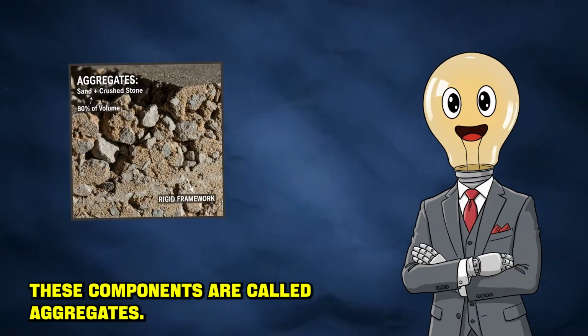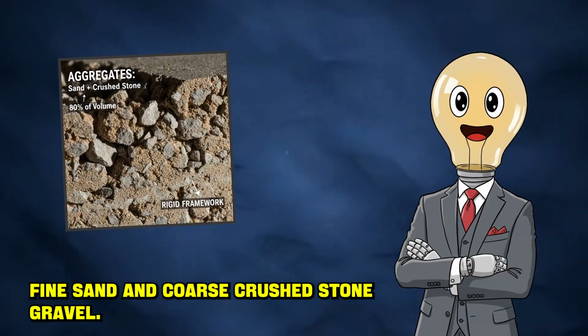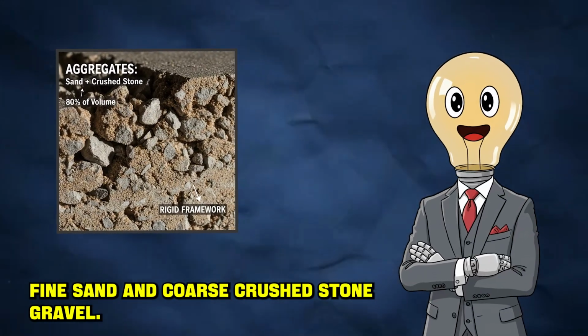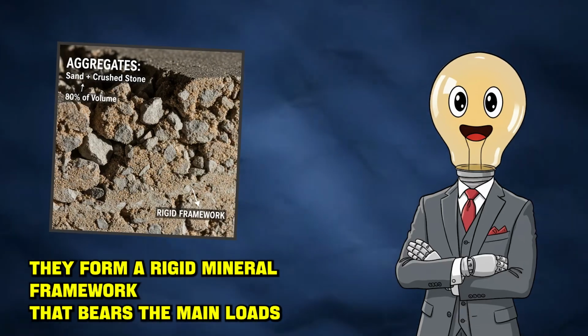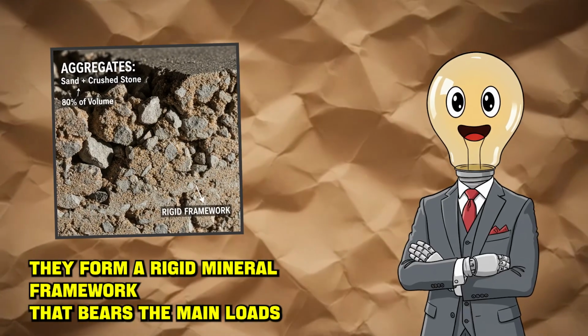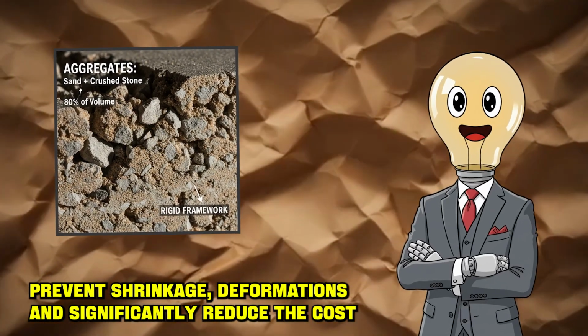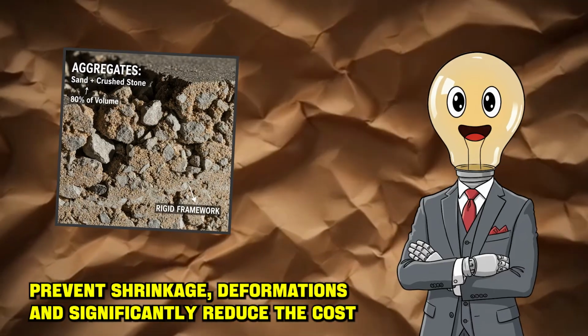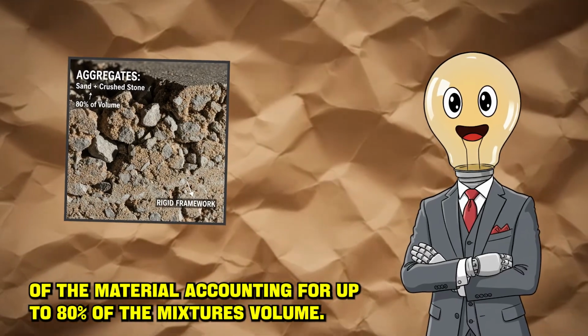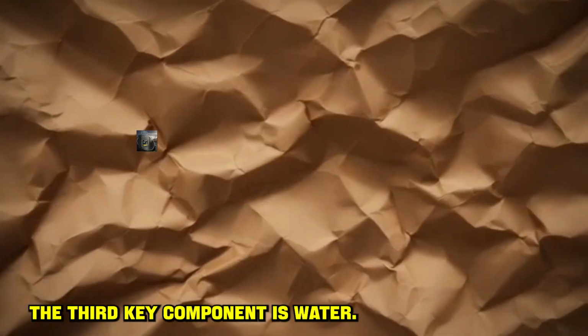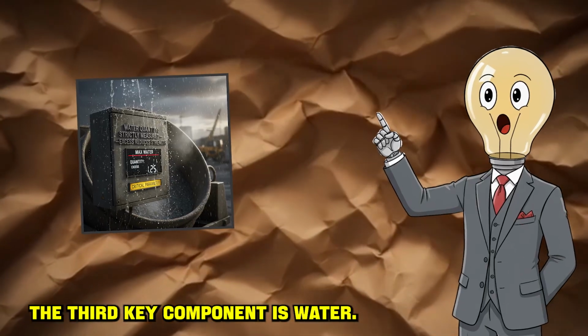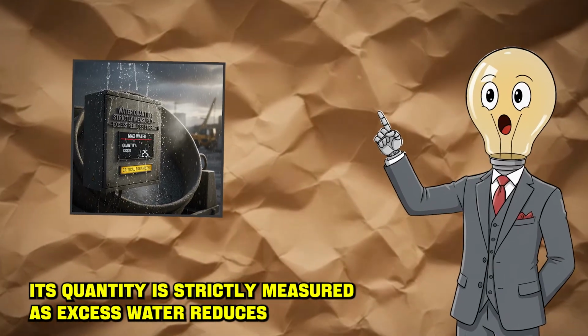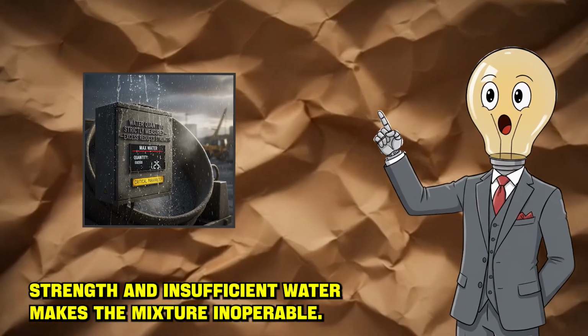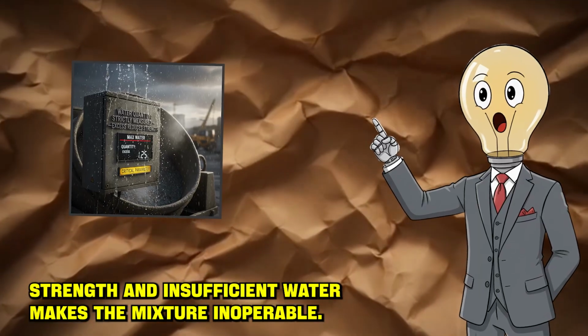These components are called aggregates, fine, sand, and coarse, crushed stone, gravel. They form a rigid mineral framework that bears the main loads, prevent shrinkage deformations, and significantly reduce the cost of the material, accounting for up to 80% of the mixture's volume. The third key component is water. Its quantity is strictly measured, as excess water reduces strength and insufficient water makes the mixture inoperable.